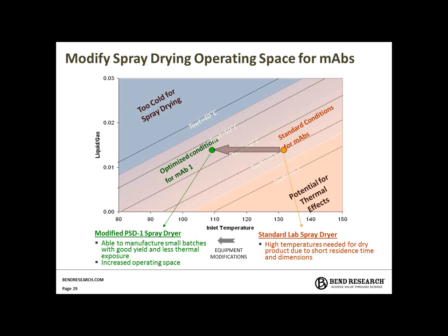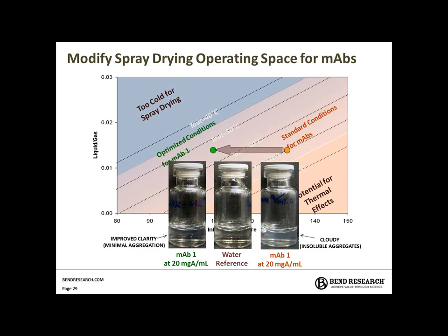So this orange dot in the spray-dry operating space Devin touched on earlier, the orange dot on the right-hand side of this plot, is the standard space that most lab-scale Buchi spray dryers operate at. We used a modified PSD1 spray dryer to drop the inlet temperature to make this a more gentle process for the monoclonal antibody to mitigate aggregation. What we found was that it had a significant impact on mAb quality after resuspension.